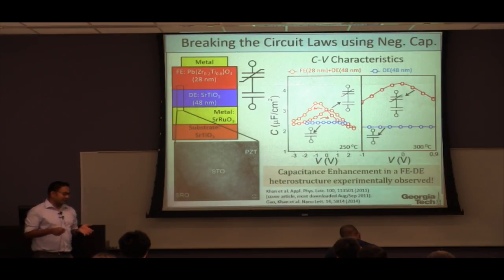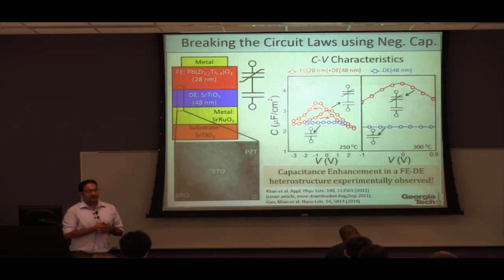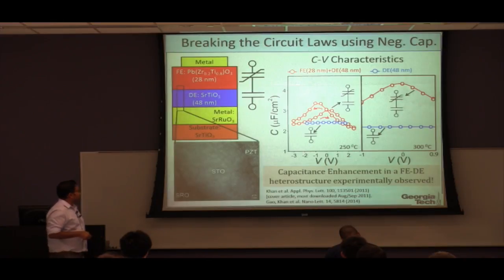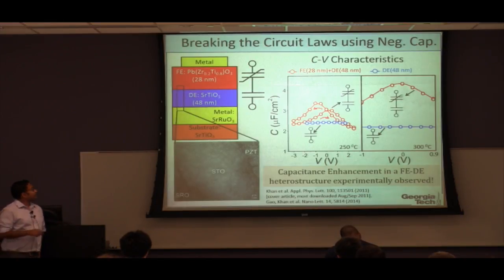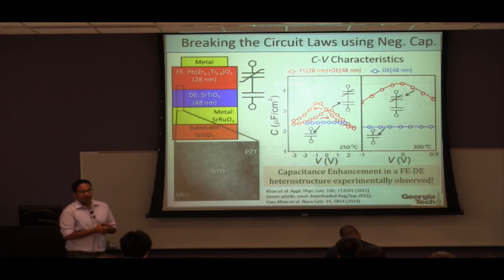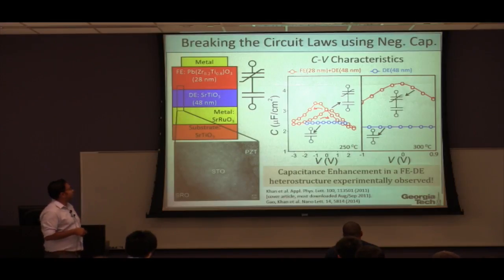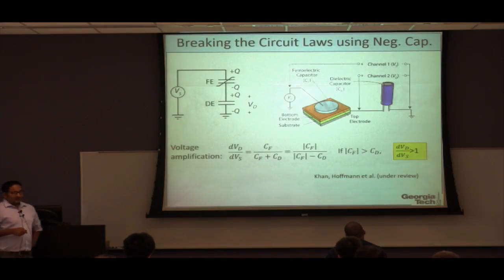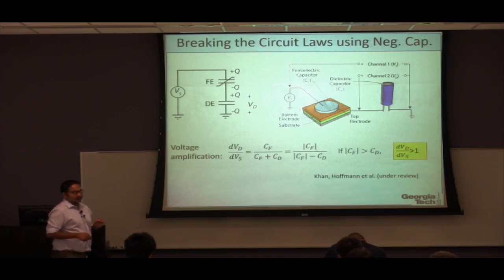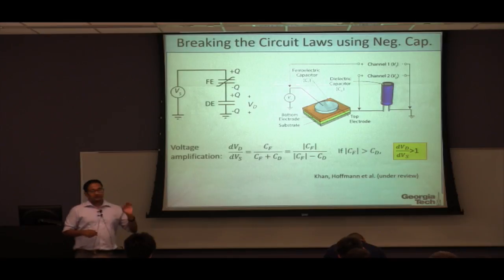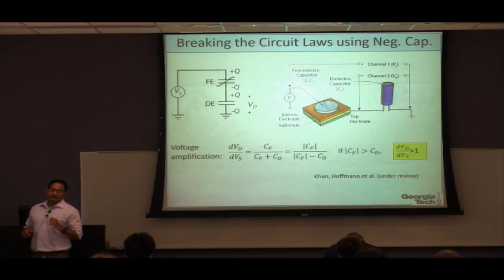And what we are seeing is a capacitance enhancement, and this essentially happens because the ferroelectric is working as a negative capacitor. So this is the first experiment that shows that with these new kinds of material, you can break the established laws of electrostatics and circuit theory. So the next experiment that we did was this. Again, the same structure, but in this case, we took a ferroelectric material and connected it in series with a simple electrolytic or a ceramic capacitor.